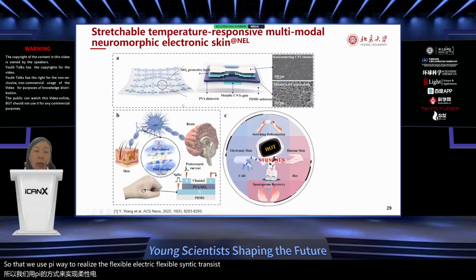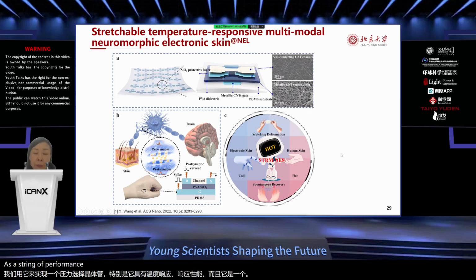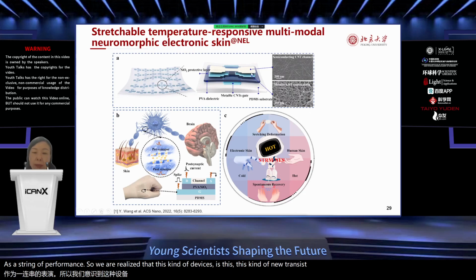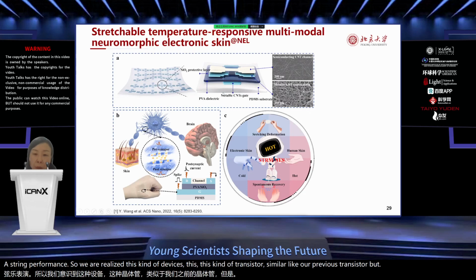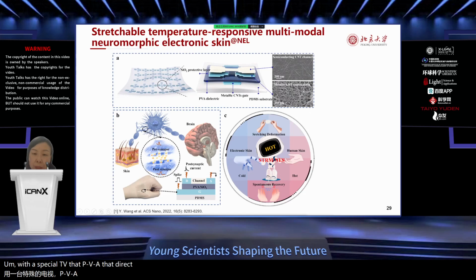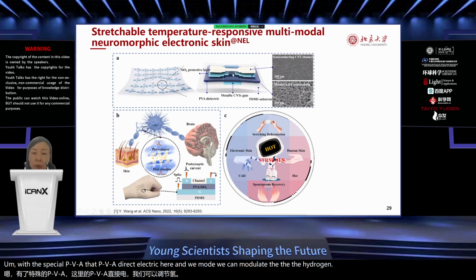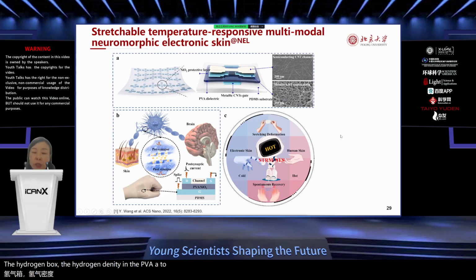So we use PVA to realize the flexible synaptic transistor, and further we use it to realize the stretchable synaptic transistor, especially with temperature responsive performance, and also it has a strain performance. So we realized this kind of transistor, similar to our previous transistor, but with a special PVA dielectric here, and we can modulate the hydrogen bonds, the hydrogen density in the PVA to change their plasticity.